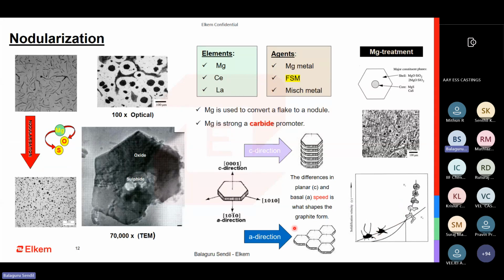The flakes kind of join together to form a nodule. So naturally, the A direction is easier to grow because of the height difference. It can more easily join. But to make sure that the C direction is growing, you need to introduce magnesium, which modifies the surface tension and makes sure that the nodule is being formed.